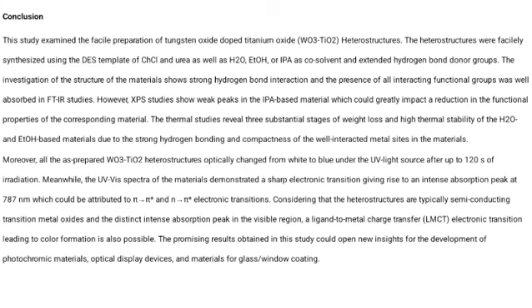Moreover, all the as-prepared heterostructures optically change from white to blue under UV light source irradiation after up to 120 seconds of irradiation. Meanwhile, the UV spectra of the material demonstrated a sharp electronic transition, giving rise to an intense absorption peak at 787 nanometers, which could be attributed to pi to pi star and n to pi star electronic transitions.